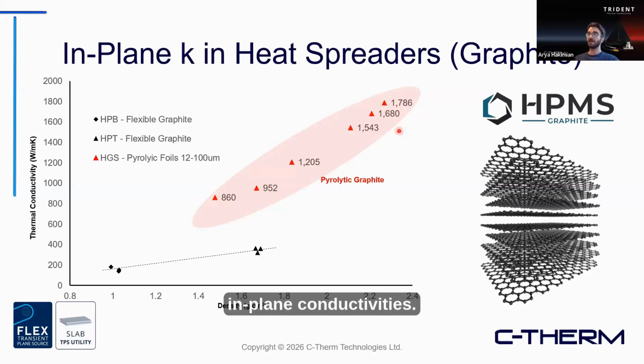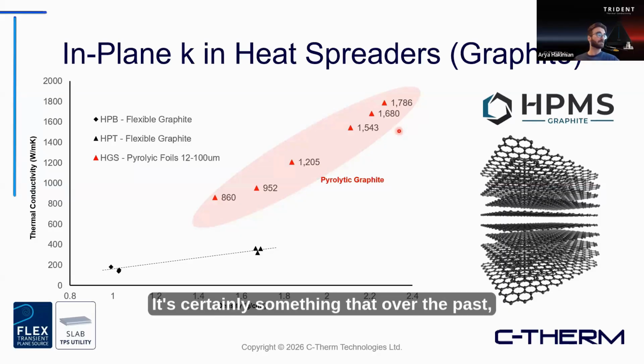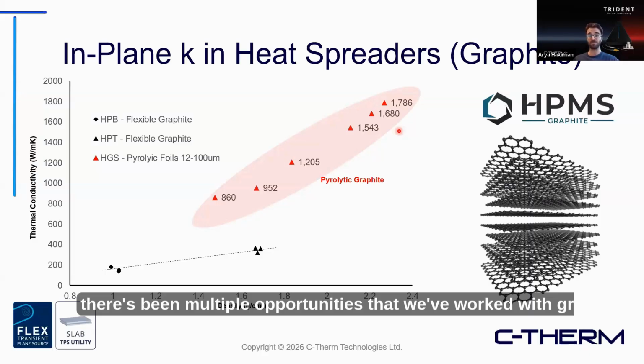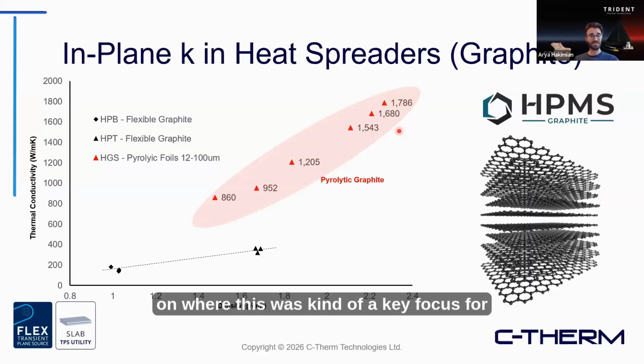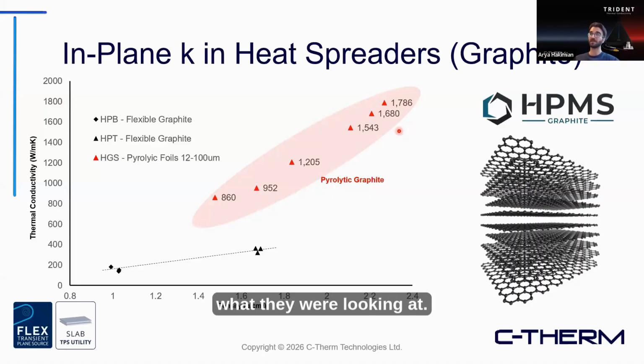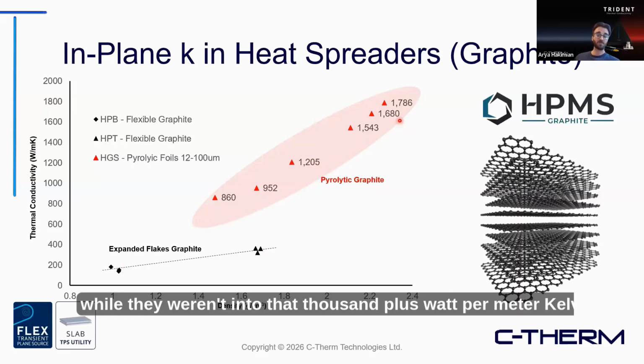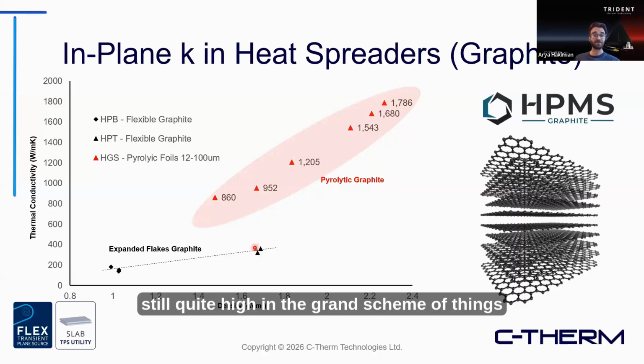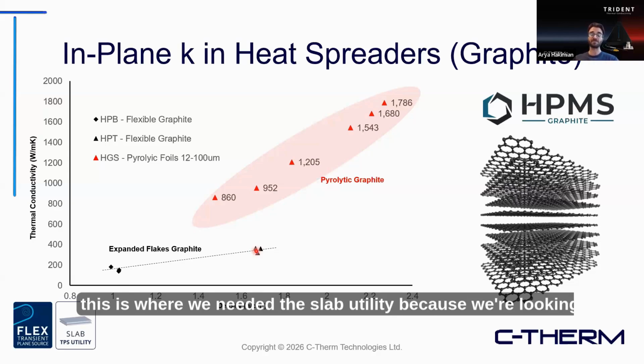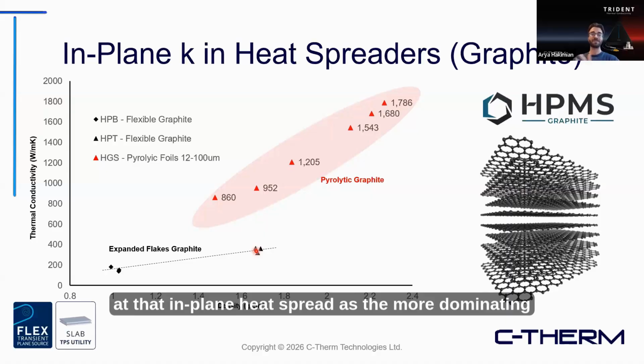This is a trend that we've seen more and more, highly anisotropic with very high in-plane conductivities. It's certainly something that over the past, I'd say definitely 6 months, there's been multiple opportunities that we've worked with groups on where this was a key focus for what they're looking at. Now these samples down here, while they weren't into that 1,000+ watt per meter Kelvin range, still, a few hundred watt per meter Kelvin is still quite high in the grand scheme of things compared to many other materials in this space. But again, to be able to assess these materials specifically, this is where we needed the slab utility, because we're looking more at that in-plane heat spread as the more dominating property of interest for these groups.